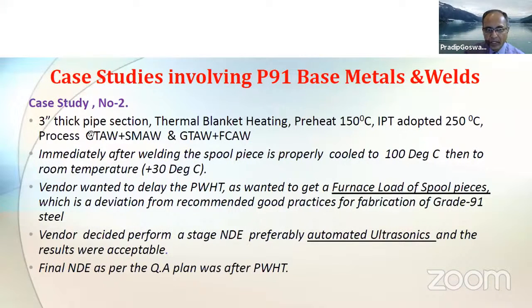Case number 2, a 3-inch pipe section, thermal blanket heating, preheat at 150 degrees centigrade. Interpass is 250 degrees centigrade. Process is TIG plus stick, as well as TIG plus flux core arc welding. Immediately after welding, the spool piece is properly cooled to 100 degrees centigrade and then to room temperature, 30 degrees centigrade. Vendor wanted to delay the post-weld heat treatment, as he wanted to get a furnace load of spool pieces, which is a deviation from normal good practices for fabrication of P91 steel. The vendor decided to perform a stage NDE, preferably automated ultrasonic, and the results were found to be acceptable. Final NDE as per the QA plan was after post-weld heat treatment.